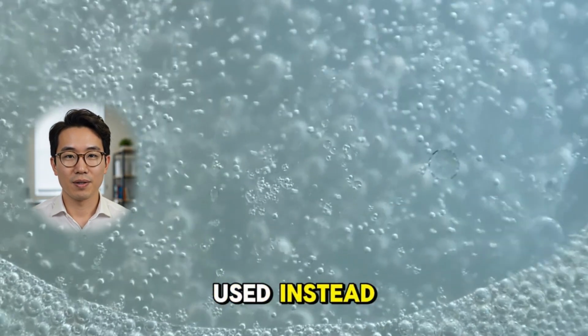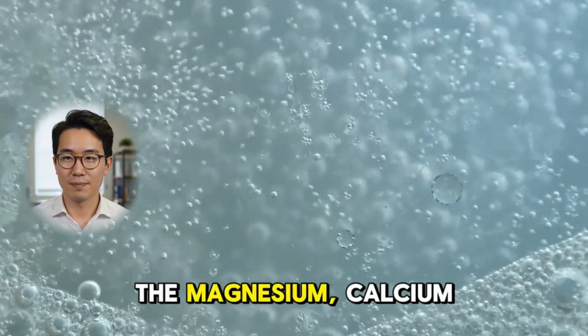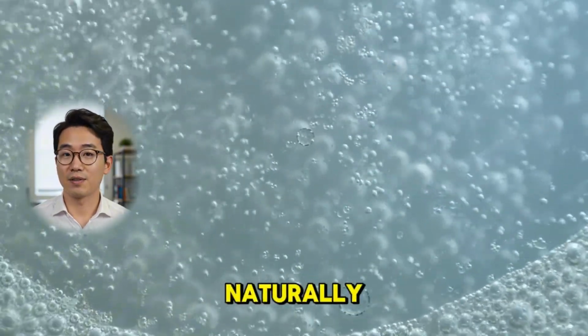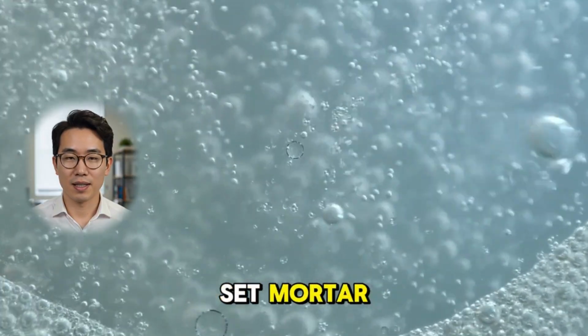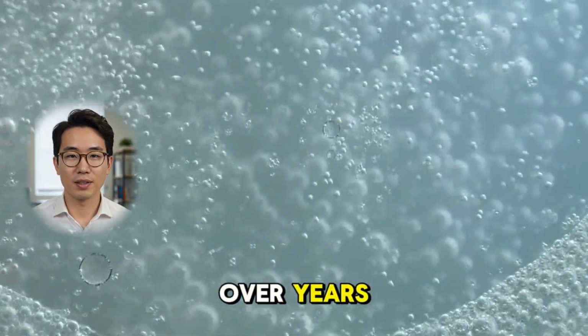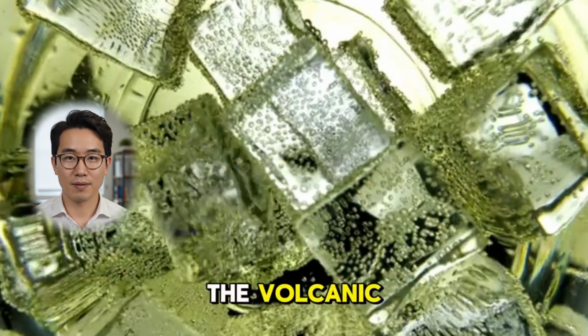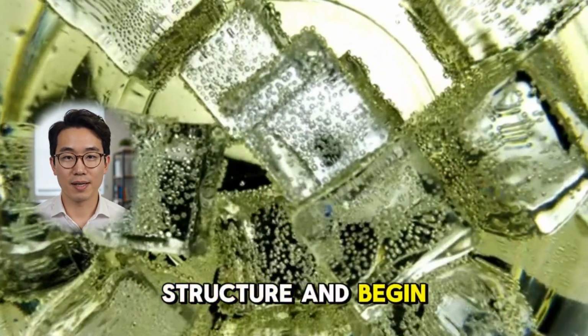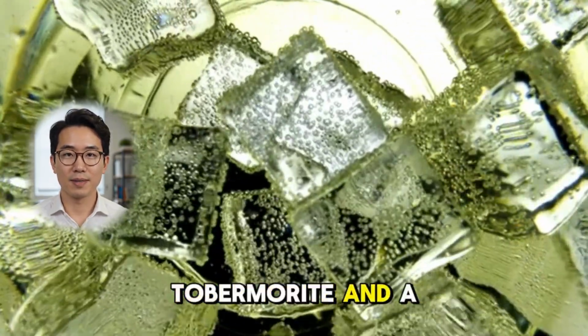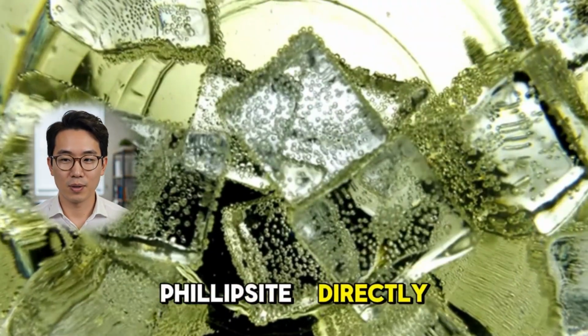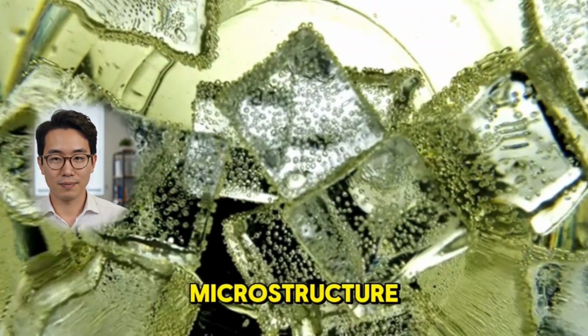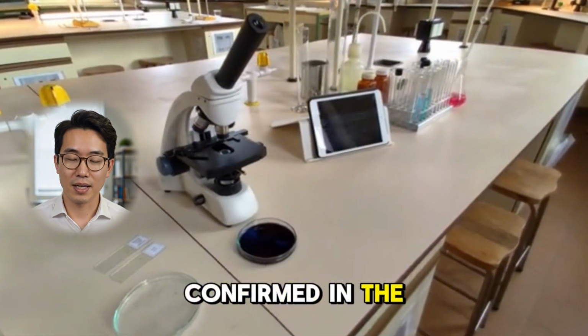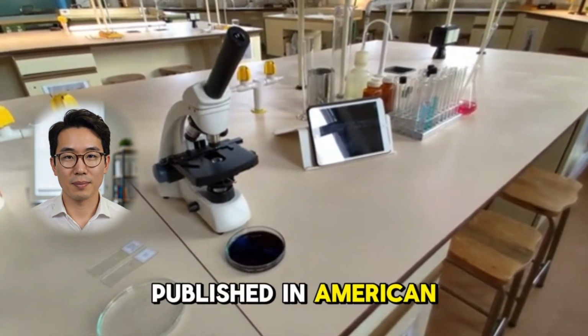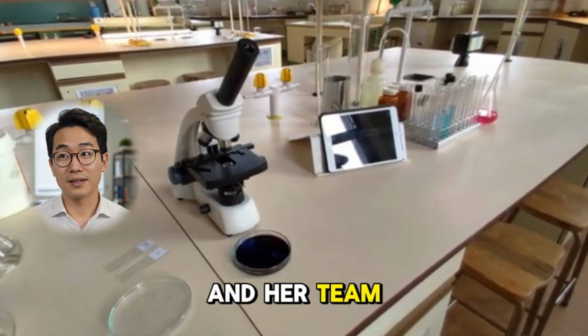When seawater is used instead of fresh water, the magnesium, calcium, and bicarbonate ions naturally dissolved in it begin moving through the set mortar. Not immediately, over years, over decades. They react with the volcanic ash deep inside the structure and begin crystallizing tobermorite and a second mineral called philipsite, directly inside the concrete microstructure. Both minerals were confirmed in the 2017 follow-up study published in American Mineralogist by Jackson and her team.